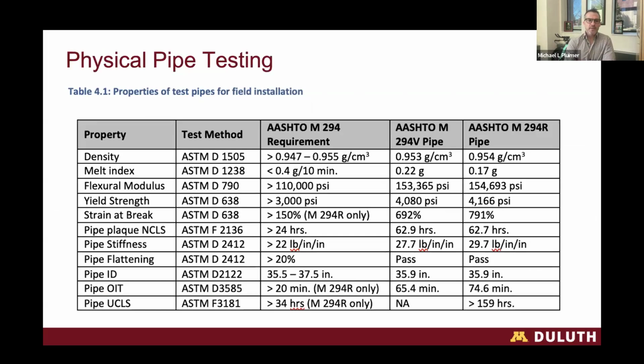The pipe material testing, we tested both pipes, the virgin pipe as well as the recycled pipe, for all of the material properties. And you can see the material performance was very, very close between these two pipes. If you look, for example, at the yield strength of the material, both over 4,000 psi yield strength, the flexural modulus, very, very close. And then from a stress crack resistant standpoint, they both performed well also. And the UCLS test requirements, we typically require 34 hours for that test on recycled materials, and we were over 159 hours on this particular pipe.